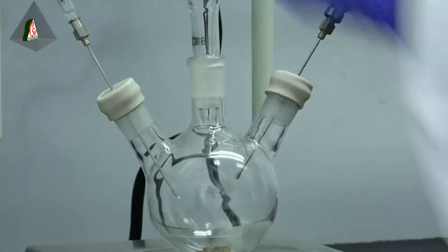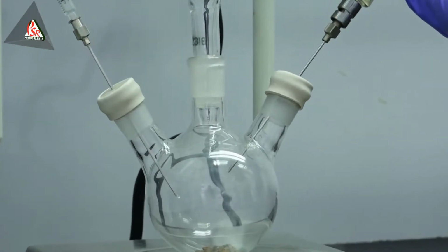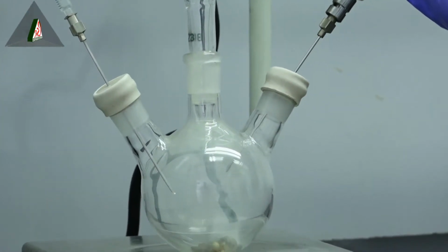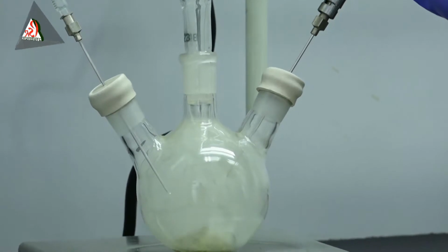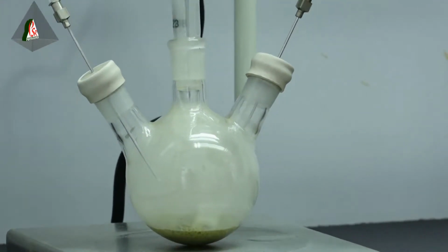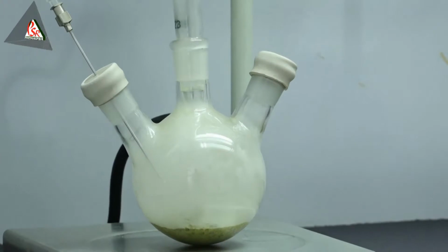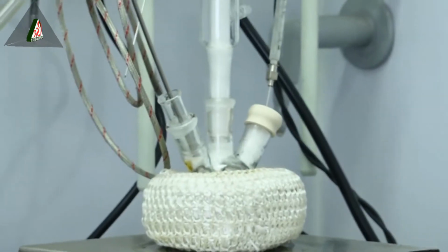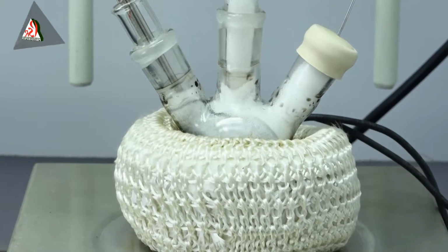The flask contains calcium phosphide. Now HCl has been injected. Soon after, the phosphine gas is generated. As you see, the phosphine has been carried out by argon and it is bubbled in the cobalt chloride solution. As a consequence, we get the cobalt phosphide.